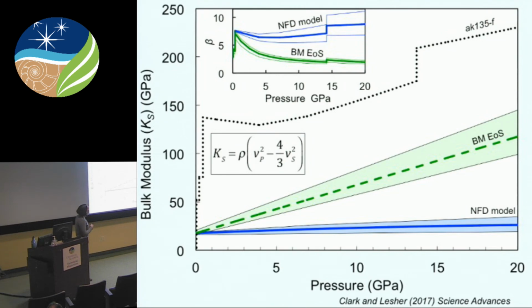Now remember, beta is the parameter that goes into these equations, so here I show you quickly the difference between beta for the Birch-Murnaghan equation of state. Because they're sub-parallel, we end up with very low values in comparison, around 2, whereas the network flexibility model remains relatively constant here. This has to do with the fact that we predict low, relatively pressure-independent velocities for the melt phase.